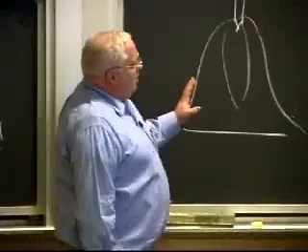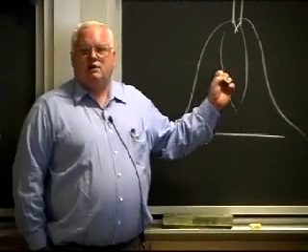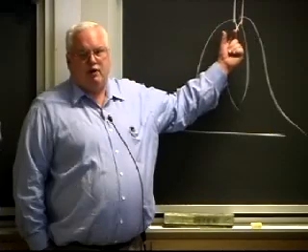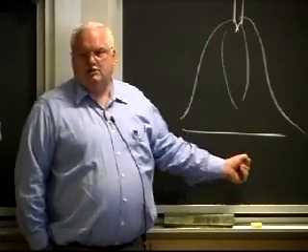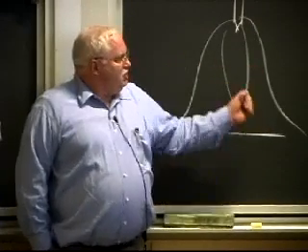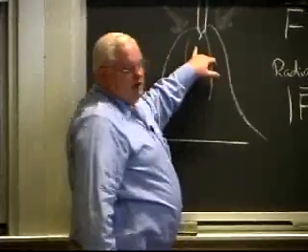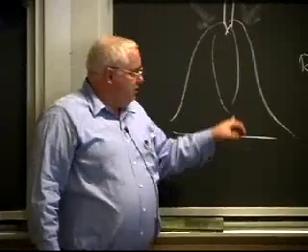Okay, let's talk a little bit more about arcs before we go into heat transfer. There is something that's very important in an arc. I told you an arc is an electrically augmented flame, and we talked about a flame essentially burning and reacting and heating up the gas, and the expansion of the gas causes the gas to accelerate towards the surface, and you have a burning velocity in a regular flame. It turns out you have the same thing in an arc. I have cold gases coming in. They get heated to 10,000 Kelvin. That's a 300-fold increase in their volume, and you expect them to accelerate down.